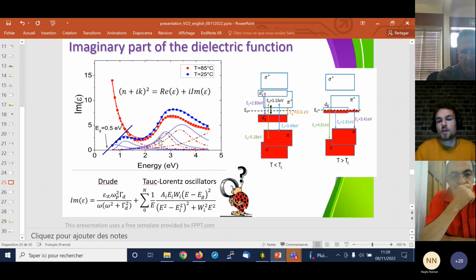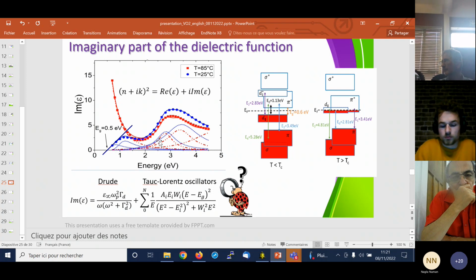Sorry, I have a question related to this. When you calculate the thickness at different temperatures, you see that the thickness is almost the same, while we have two different phases. One of them is monoclinic, the other one is tetragonal. So it means that the volume actually doesn't change when you go from one phase to another. And is that the reason that you see the peak in XRD at the same two theta?